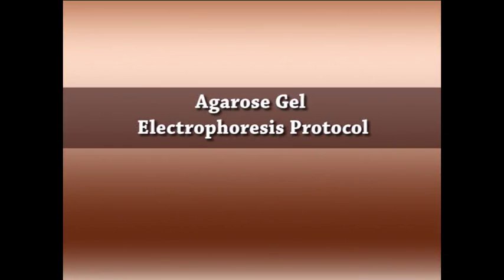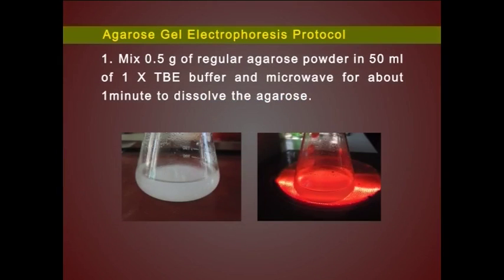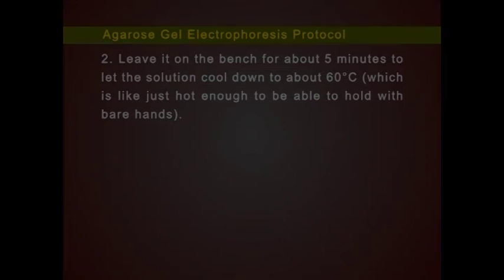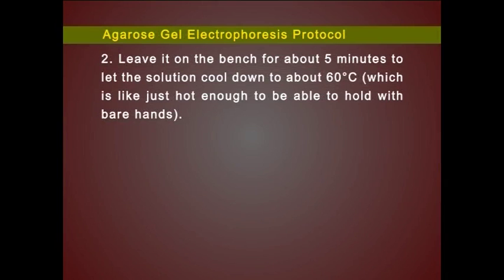Let us now see the agarose gel electrophoresis protocol. First, let us mix 0.5 gram of regular agarose powder in 50 ml of 1x TBE buffer and microwave for about 1 minute to dissolve the agarose. Then leave it on the bench for about 5 minutes to let the solution cool down to about 60 degrees Celsius, which is just hot enough to be able to hold with bare hands.